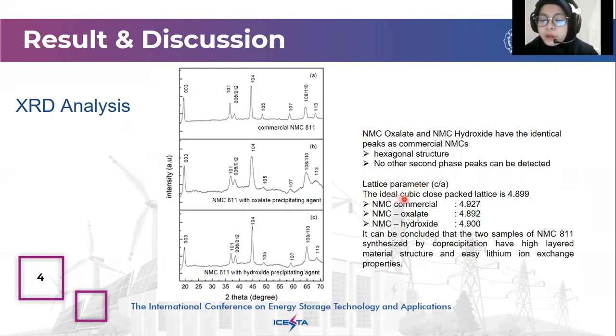the ideal cubic close pack lattice has a value of 4.899, and the greater the value of the C per A ratio, the more regular the structure will be, and the easier it is for lithium ion exchange to occur. The value of C per A of NMC commercial is 4.927, NMC oxalate is 4.892, and NMC hydroxide is 4.9. From this result, it can be concluded that the two samples of NMC 811 synthesized by co-precipitation have a high layered material structure and easy lithium ion exchange properties.